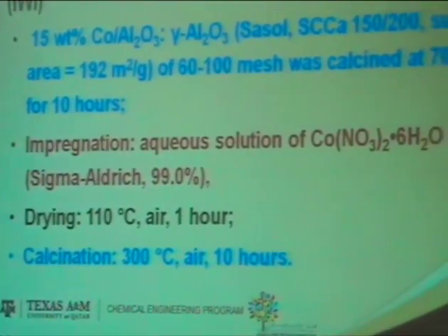Okay, so the catalyst was prepared by conventional incipient wetness impregnation, with an alumina support from Sasol and 15% loading. Usual, not so exciting anything here: calcination, drying. Pre-treatment conditions are shown here in detail.